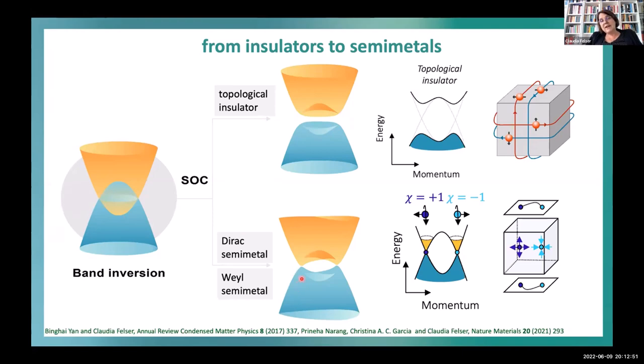But sometimes we have higher symmetry in the crystals, and then depending on the symmetry, maybe not the whole area is forbidden. So we don't end up with an insulator, we more end up with a semimetal where some areas are still overlapping or degenerate. And depending on where these points are, we call them Dirac semimetal or Weyl semimetal. So a Dirac semimetal normally has four-fold degenerate states here. So we have two crossings lying over each other, so we don't see this directly. But in Weyl semimetals, we also always have pairs of these crossings.